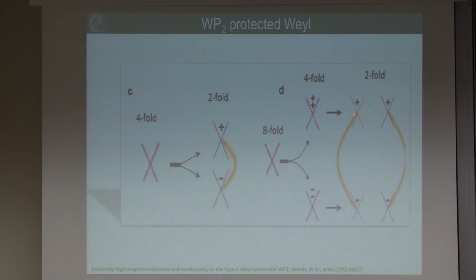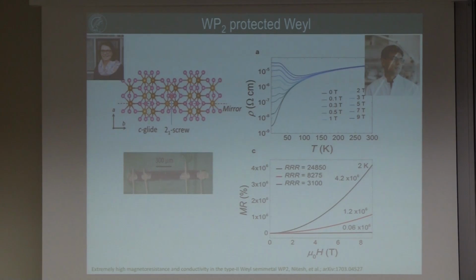So we have two Weyl points which have the same chirality close to each other, and the different chiralities much farther from each other. So we expect much larger surface state Fermi arcs, but also a higher protection of these Weyl points, because they cannot annihilate each other so easily. They have the same sign.